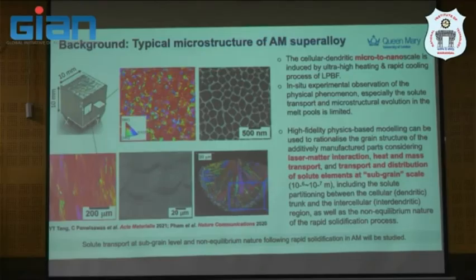So we'll study this solute trapping, or solute transport, at sub-grain scale and try to understand the non-equilibrium during or after rapid solidification. So what we do, we suspect why the new design superalloy is crack free. We try to observe using first X-ray synchrotron diffraction imaging at the light source at Harwell in Oxford, in combination with atom probe tomography in the as-printed condition,